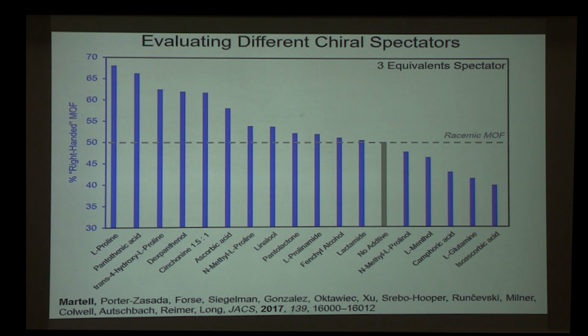In this experiment, 3 equivalents of spectator were added in each case. And what's quite promising that you can see is many of the spectators indeed induced the MOF to grow preferentially as one enantiomer. But what's not promising is that these numbers are not very close to 100%. We wanted to get closer to 100% enantiopurity.